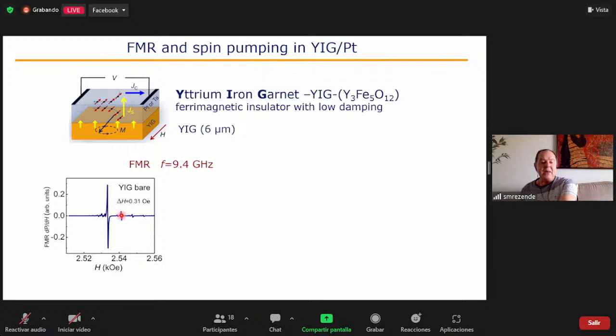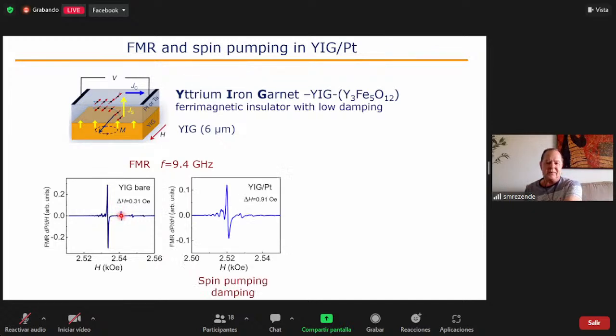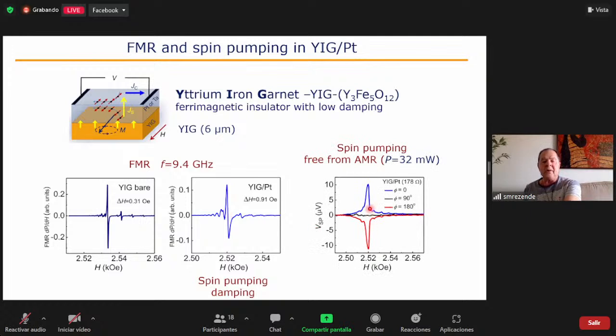It has several peaks because YIG has a very small damping. Because it has very small damping, it has spin waves, and the spin waves produce standing waves. When we put platinum, all peaks broaden because of the spin pumping damping, but we detect a very clear and strong signal. Notice that this is measured directly with a voltmeter. There's practically no noise here.